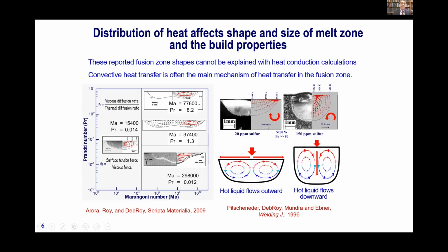What's the purpose? Take a simple thing like geometry. Seems very simple, right? But depending on the process variables, you can have a hemispherical pool. You can have a pool whose bottom shape is like a first bracket, or you can have one like W, depending on a parameter called Marangoni number, which tells us the intensity of surface tension driven flow, and Prandtl number, which is simply a ratio of viscous diffusion to thermal diffusion rates.